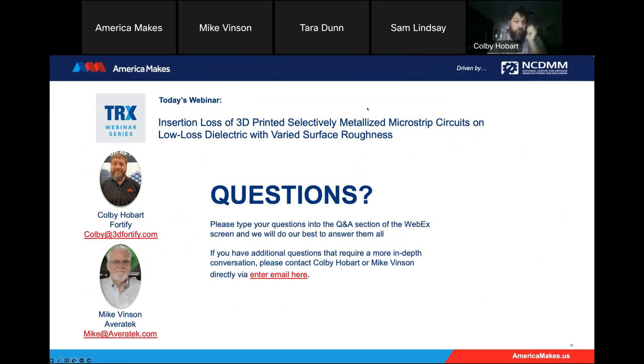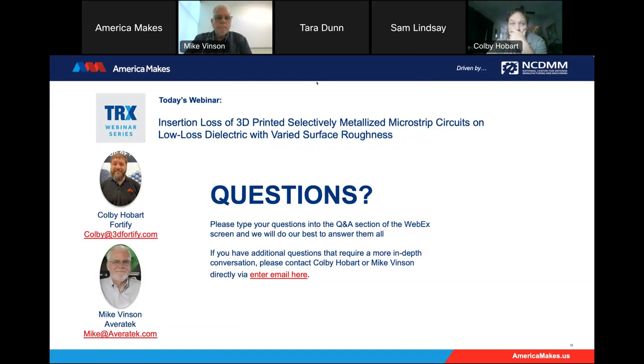Thank you gentlemen, that was a great presentation. I'll now head into the Q&A session. If you have questions for our presenters and have not done so already, please type them into the Q&A space. First question: how thick can you make the metal on these parts? These are fully additive metals, so we can plate them to whatever thickness the customer would like. We typically plate around 30 microns or one ounce copper; half ounce and quarter ounce are doable, but we can also do extremely thin metals such as 100 or 200 nanometers when those resistances are sought.